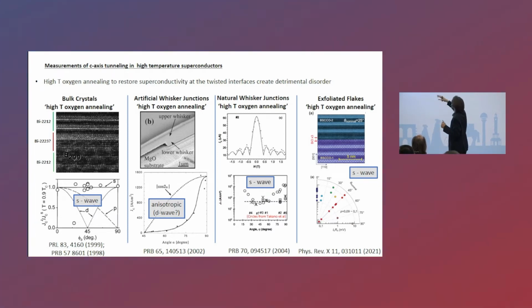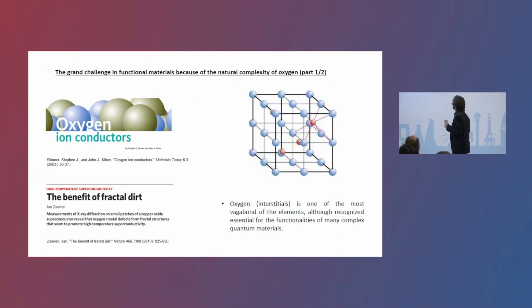All these methods showed that the junctions, when they are realized, are basically insulating. What they do is restore the superconductivity by introducing oxygen at very, very high temperature. So they have these things in common. However, we know that cuprate materials are very sensitive in the millielectron-volt energy range and are very sensitive to oxygen. Some of them, like lanthanum copper oxide and many others, are oxygen ion conductors, so the oxygen is thermally mobile.